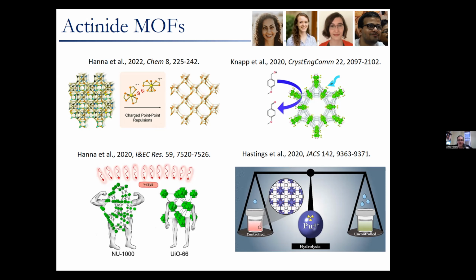It really requires a very controlled addition of water to the system, because you need water in order for the assembly to occur. But if you have too much water, then you get uncontrolled polymerization of the hexameric nodes. And instead you get the plutonium polymer, or the plutonium colloid, instead of any important structure. So that was something we were really proud of and continues to be an avenue of research in my group.